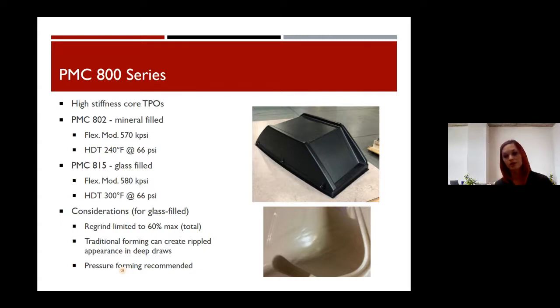It's a glass filled TPO. It's short glass filled, and it gets your HDT up to 300 degrees. So we see a lot of fan shrouds in 815. It's close to some engine components, parts that get hot. It's also really stiff, a stiff feel. 580,000 PSI on the flex mod. The one consideration with it is the rippling. So it kind of thins a little unevenly with the glass. So you can see in that bottom right-hand corner, it's not the prettiest part. It's got a little bit of wrinkles to it.